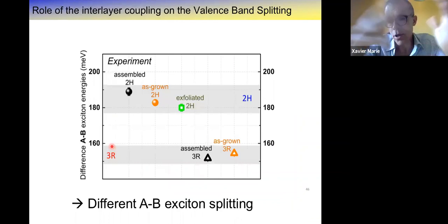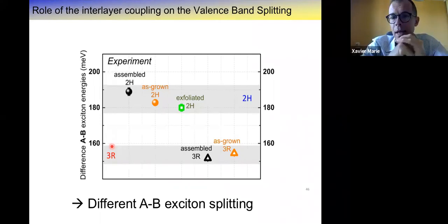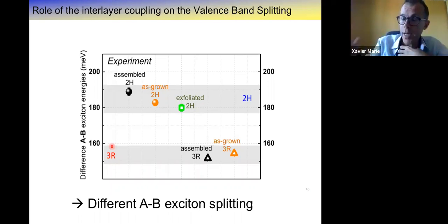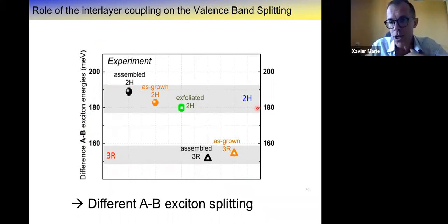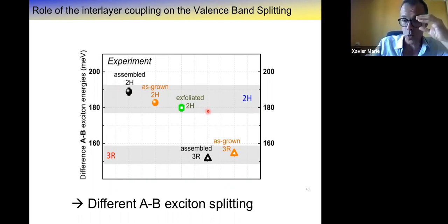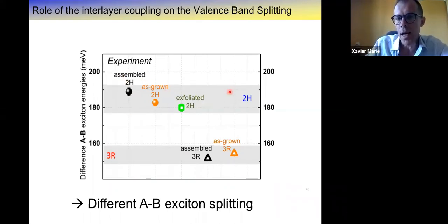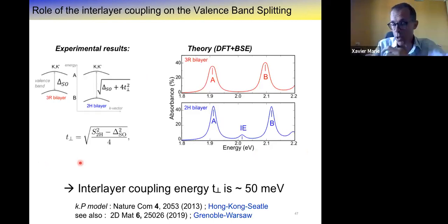Another consequence, before switching to the control of this interlayer exciton by electric field: if you have coupling, in fact, you expect a change of the energy of the valence state because you have this hole tunneling. And indeed, if you look at the difference of energy between the A and B exciton in the measurement for the 2H stacking or for the 3R stacking, you clearly see that for 2H stacking, whatever the way you obtain it, exfoliated, as-grown CVD or assembled CVD, the splitting between A and B is 30 millielectron volts typically, larger than the splitting you get for 3R stacking. And this is consistent with this hybridization of the hole tunneling, which is at the origin of the coupling between the two layers.